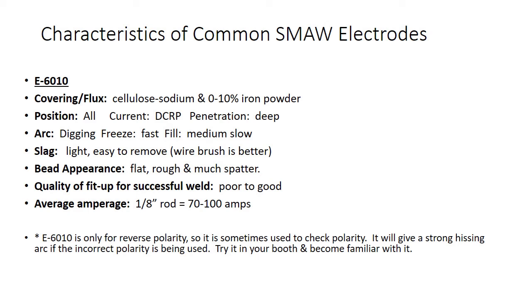So here's a characteristic of some common electrodes. 6010, cellulose sodium. You might have a little iron powder in there. It's an all position. It's got a digging arc. It freezes fast. It fills medium to slow. You're not really putting a lot of metal in there. It's a light, easy slag. It's a rough bead appearance.